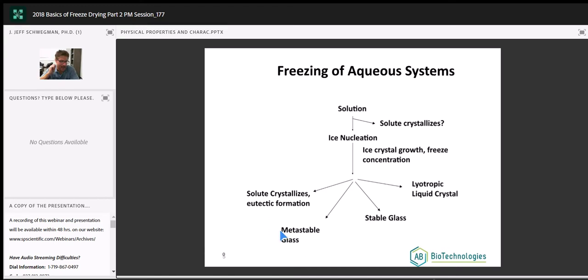Sometimes we might see the metastable glass form. And when we say metastable, we technically mean unstable. This is a glassy phase that forms, so no order to this system. However, it should have crystallized and formed the eutectic. That's its most stable free energy state. For a number of different reasons, it didn't do that, but it should be there. The problem is, if we freeze dry a product and keep it in its metastable state, over time, it's going to crystallize. The laws of thermodynamics state that that's going to happen. And when it does crystallize, it's going to wreak havoc on your formulation. So this is where we'd be talking about adding thermal treatment or an annealing step to get rid of this metastable state.